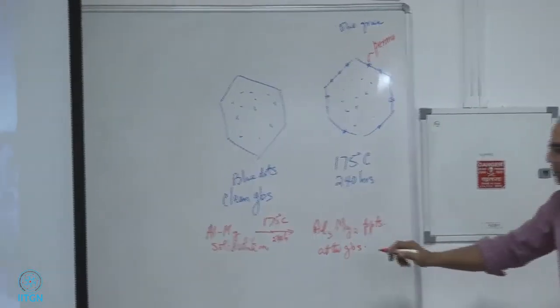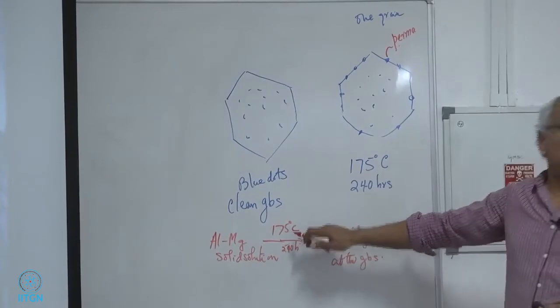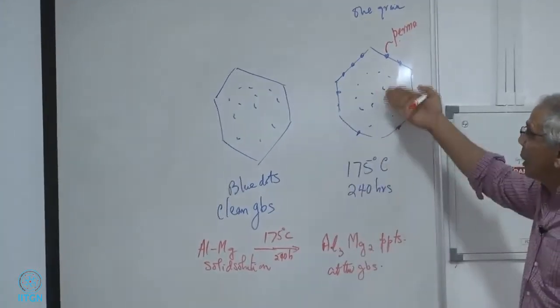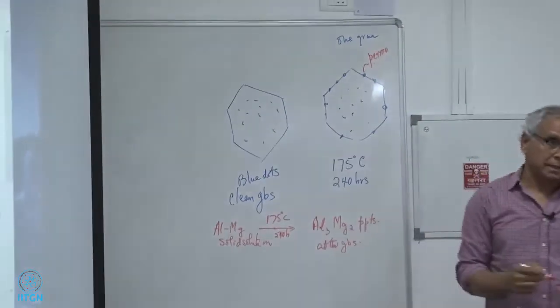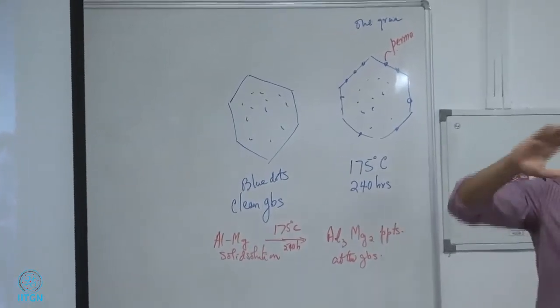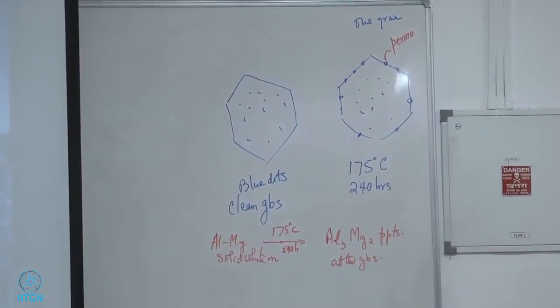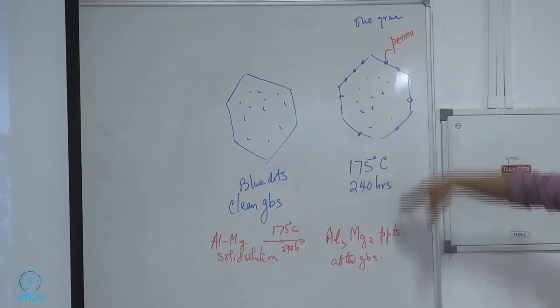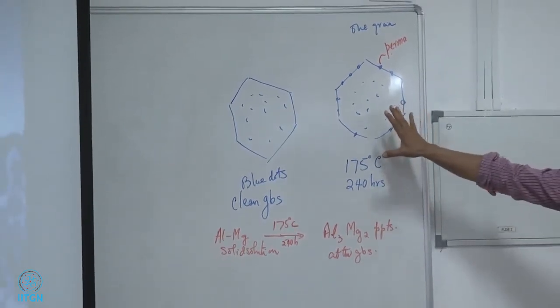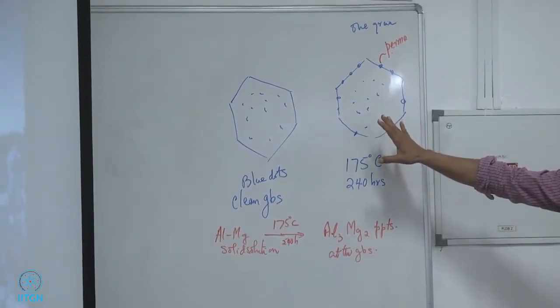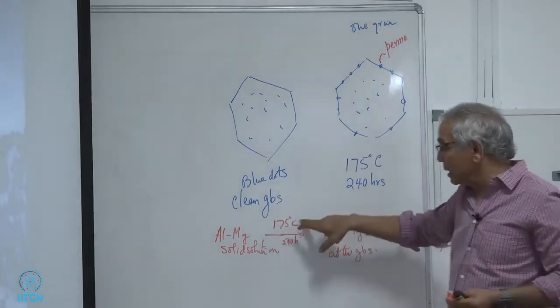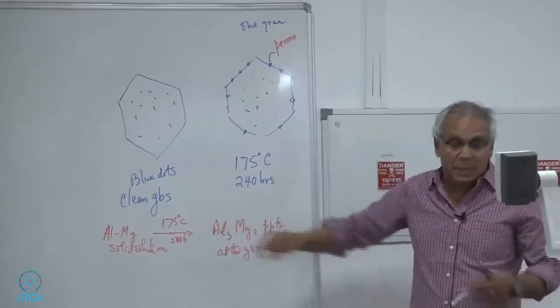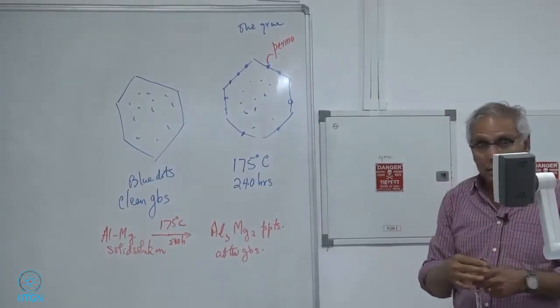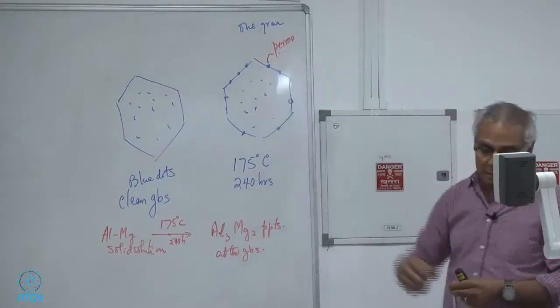Okay? But if I go to 400 degrees C, they may all go back in again because the temperature is too high for the solubility. Okay? But if I just cool it to room temperature, they will still stay there. Okay? And if I leave it at 175 degrees for 1,000 hours, they'll get bigger and bigger. These will get bigger and bigger.